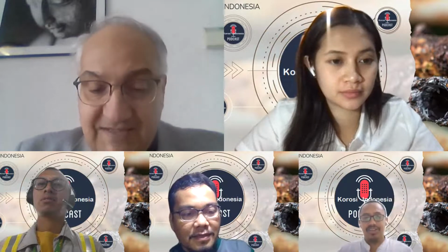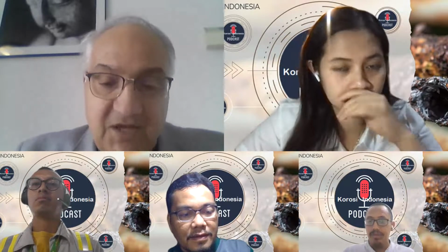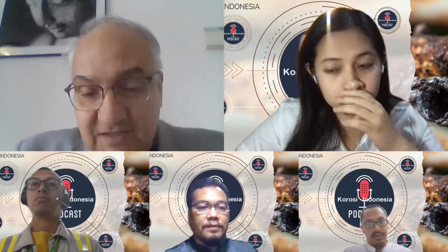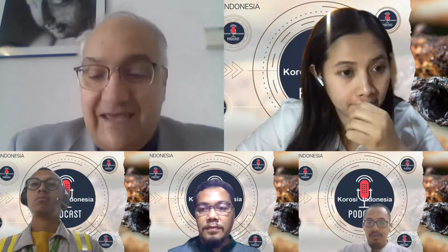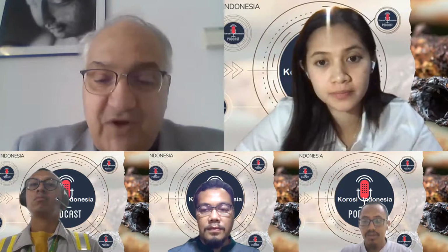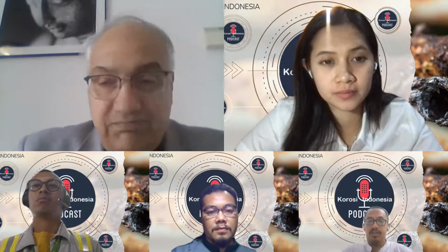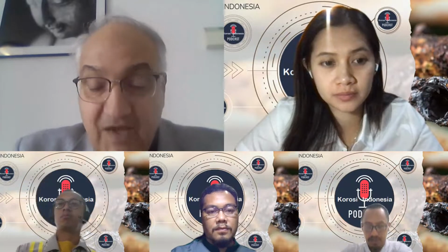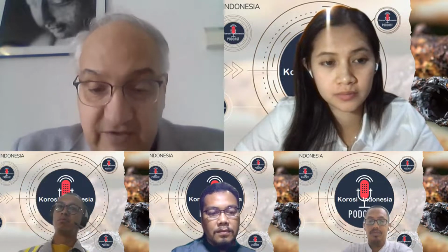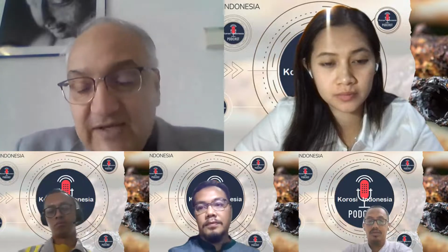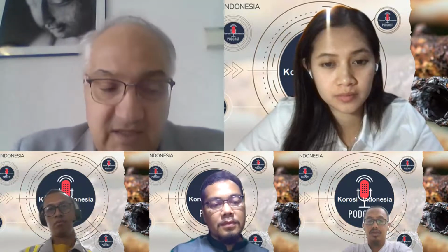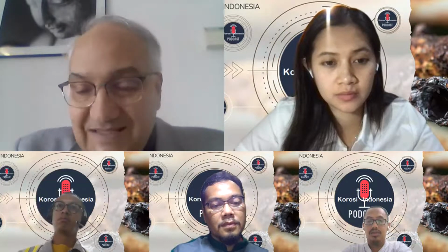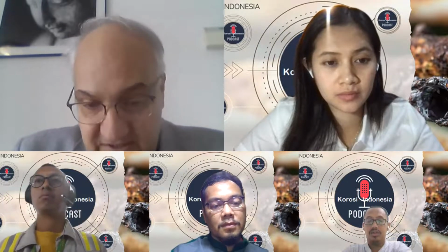Yes, thank you. I want to add to Dr. Martin's points. I agree, but don't forget that NDT methods are basically used based on the assumption that pitting, for example, is the same, whether it is coming from MIC or from, I don't know, atmospheric corrosion. Unfortunately, the morphology of the failure in MIC cases is not that different from abiotic cases.